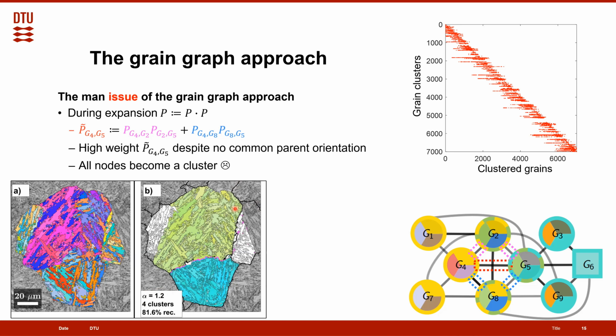And for example, this cluster here, we can see that it actually went far beyond the boundary of what should be the austenite grain. And as a result, we actually were not able to afterwards calculate a parent orientation here because we didn't find any good match. The same has happened over here. We couldn't find any parent orientation. We can generally see that this clustering is basically extending over the boundaries of the prior austenite grain. And this is, of course, a big problem. We call this over-clustering. I'm not sure if this is a proper English word, but it's quite intuitive, I would say.